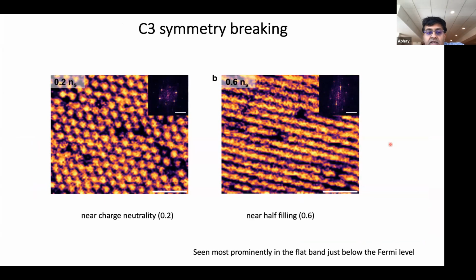And quite interestingly, we found that there is an entire range of doping where the threefold rotational symmetry is broken. So this is near charge neutrality, where you can see over a large area the threefold rotational symmetry. And then this is close to, but not exactly at half filling. This is at 0.6 filling. You can see the local density of states, and it completely breaks this threefold rotational symmetry. So you can see nice lines that are elongated in one of the three principal directions.